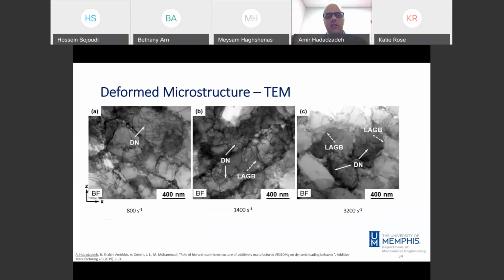Again, since we are deforming the material, we have an increase in the density of dislocations because of dislocation motion and evolution of new dislocations. By increasing the strain rate, we'll have more heat in the material. The temperature will rise because of the effect of strain rate. Now, there's another driving force for motion of dislocations. And because of the temperature rise, now the dislocations can rearrange and we can have recovery. Because of the rearrangement of dislocations, low angle grain boundaries start to develop in the material.